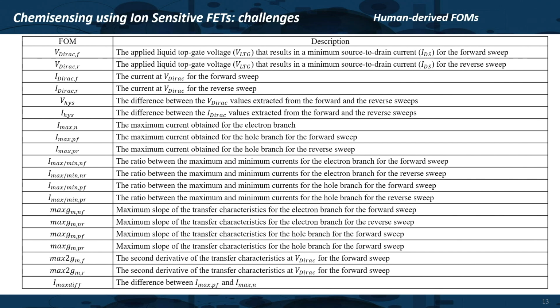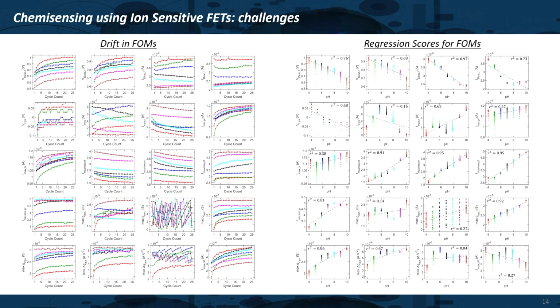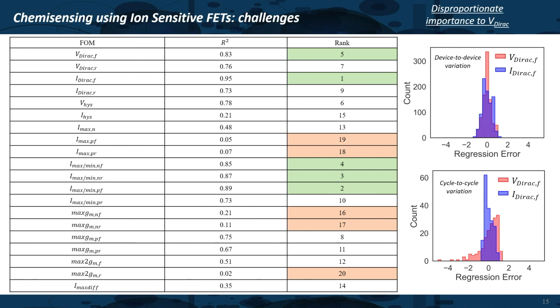There's a huge list of parameters that you can extract, right? The minimum current, the maximum current, the on-off ratio, because it's a transistor, so you can really extract a lot of information. But even if I look into how each of these parameters changes as a function of all this device-to-device variation, I can probably go ahead and rank them. And I can find that, oh, okay, V Dirac has rank 5, but I Dirac is rank 1, and that's good. But even with the first-rank figure of merit, I don't get to 100% accuracy because it is still drifting.